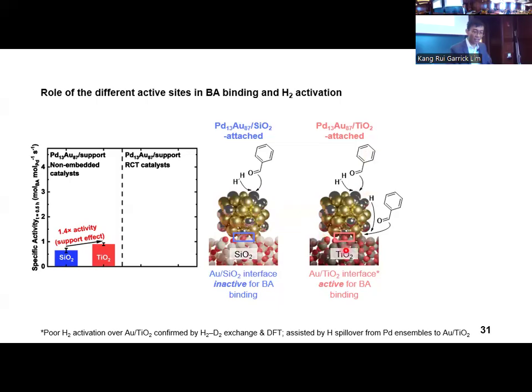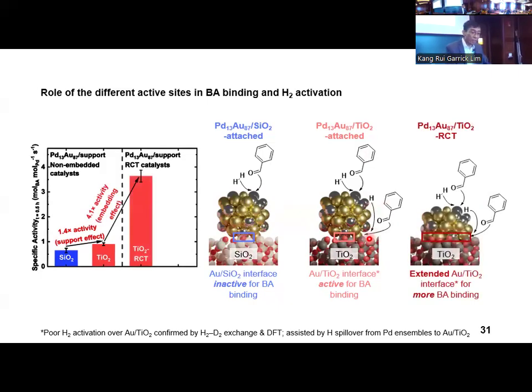Since the gold-titanium interfacial sites activated hydrogen poorly from our experimental results, we deduced that the benzaldehyde bound at this interface was hydrogenated by hydrogen spillover from palladium ensembles on the nanoparticle surface that activated hydrogen. Importantly, partial nanoparticle embedding into the titanium support enhances activity by a further 4.1 folds as the nanoparticle support interfacial perimeter, and thus the number of gold titanium interfacial sites, was increased, which enhanced benzaldehyde adsorption capacity and reaction at the interface.